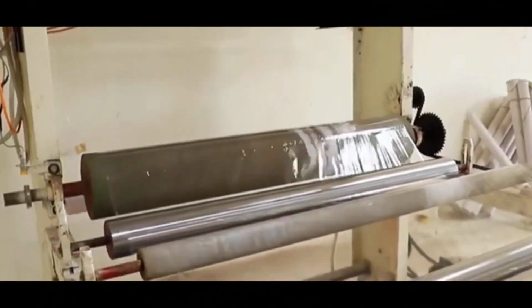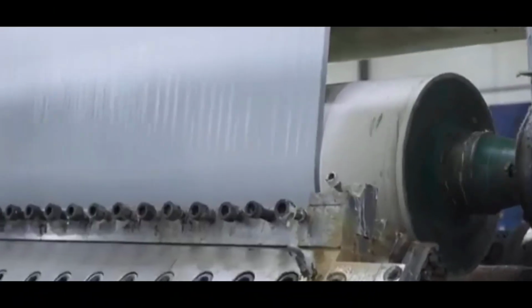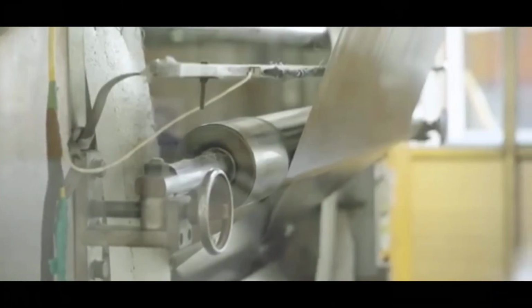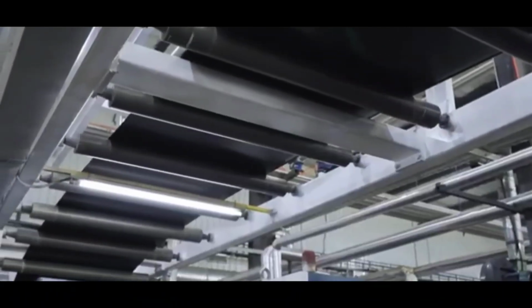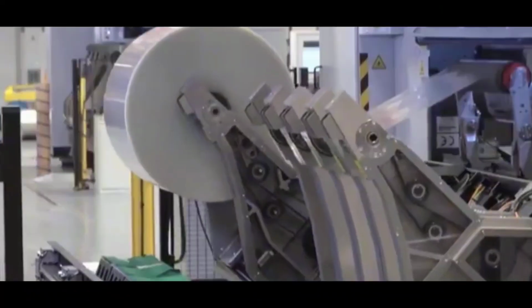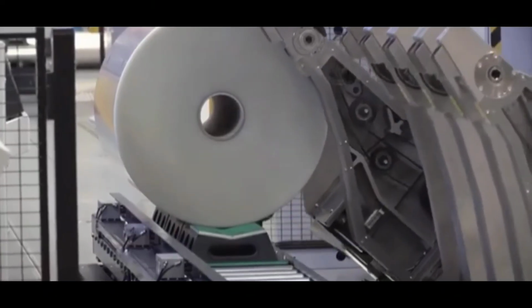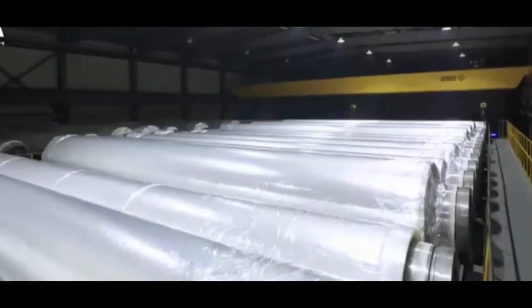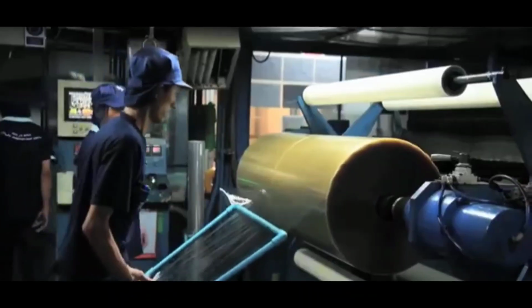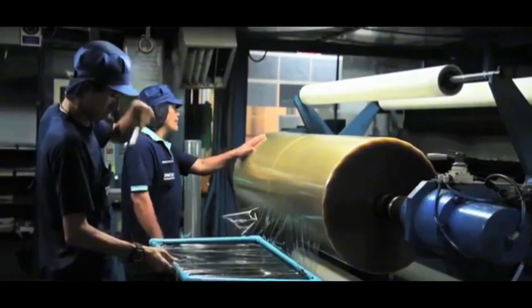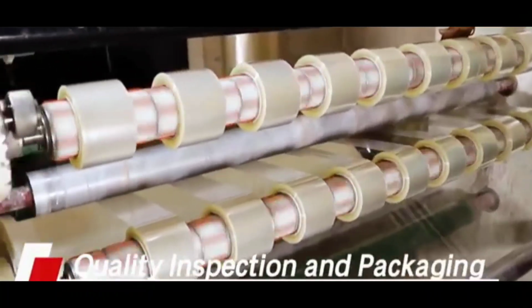After coating, the film travels through a heated drying chamber maintained between 180 and 220 degrees Fahrenheit, where solvents or moisture are evaporated, leaving behind a clear, uniform, and firmly bonded adhesive layer. Some premium tapes are coated twice, a base layer that strengthens adhesion to the film, and an outer layer optimized for performance during application. As the coated film exits the drying chamber, it is cooled and rewound into large, flat, glossy rolls, smooth, dry, and ready for the final finishing stages.